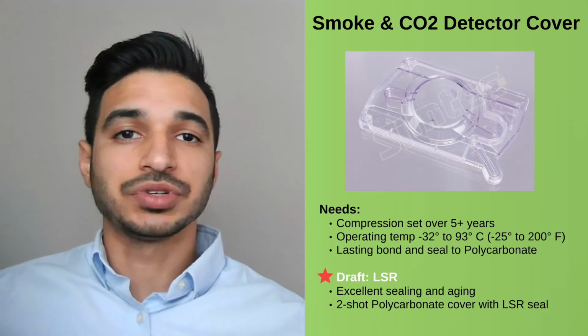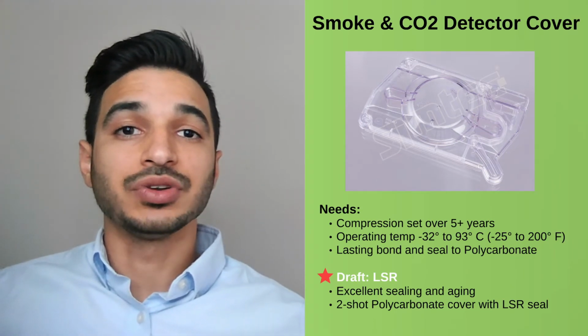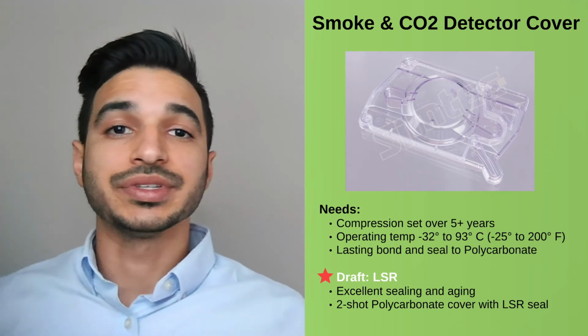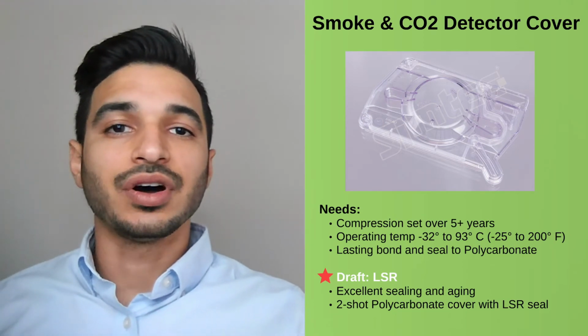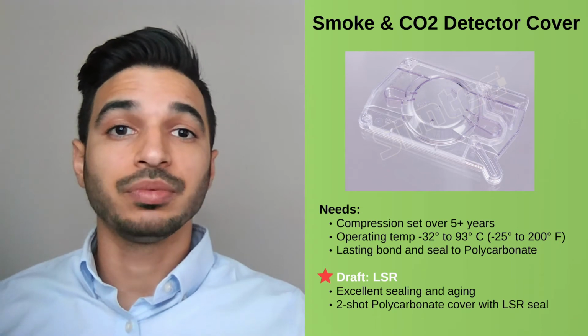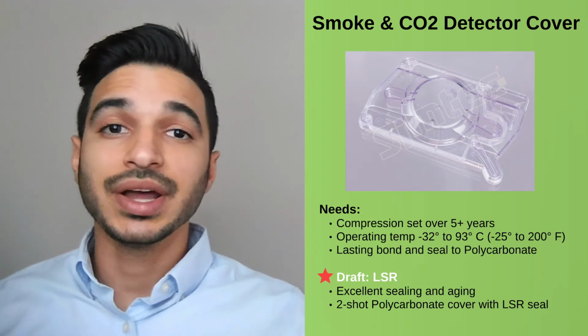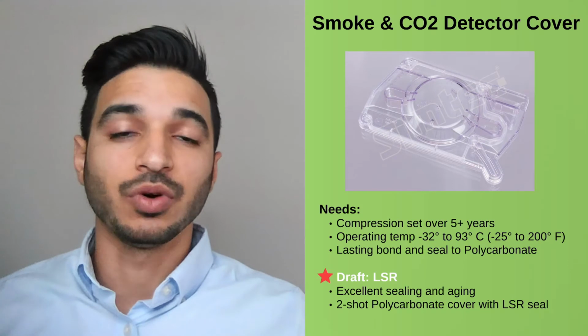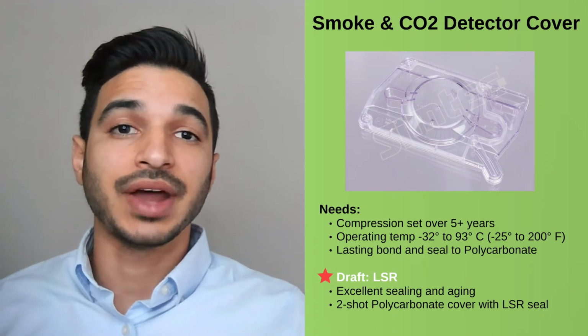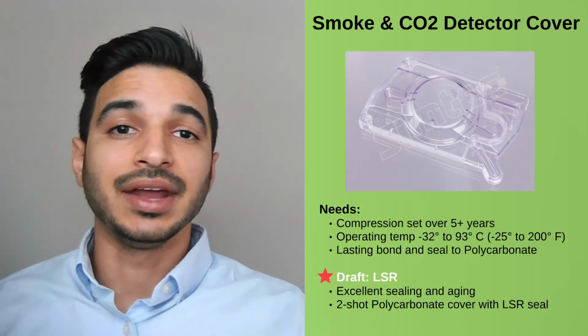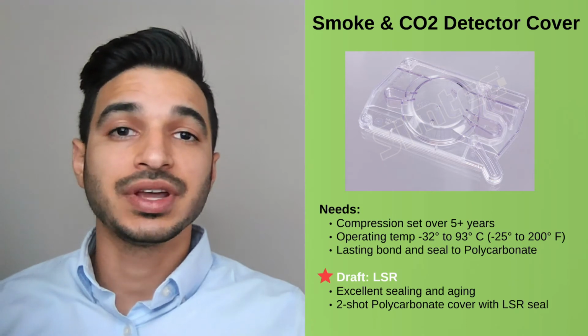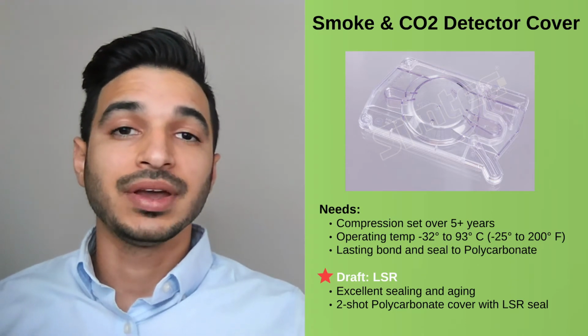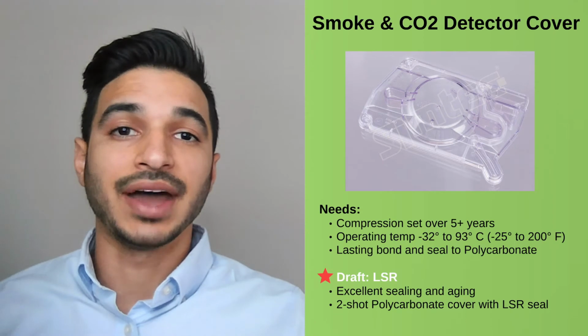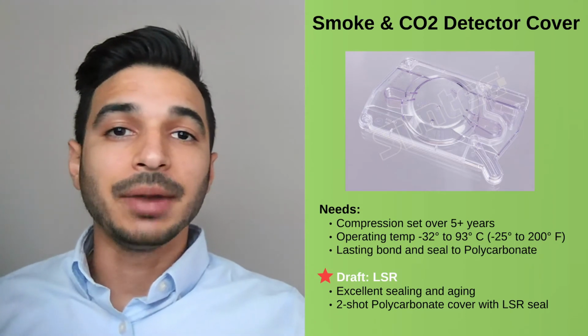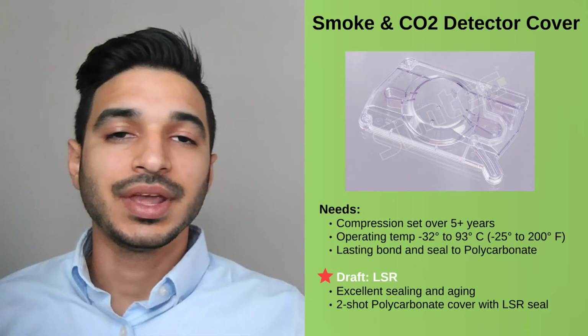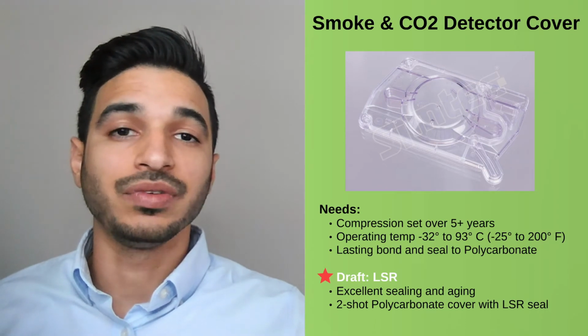So looking at both options, it was selected based on two main points that LSR was the best choice. The reason is that LSR has superb compression set, which again translates into its sealing performance. So with silicone having less than 20% and withstanding over the given temperatures and over the lifetime needed, LSR was the best choice for that reason. And also, it bonds very well to polycarbonate and can maintain that bond over the lifetime.